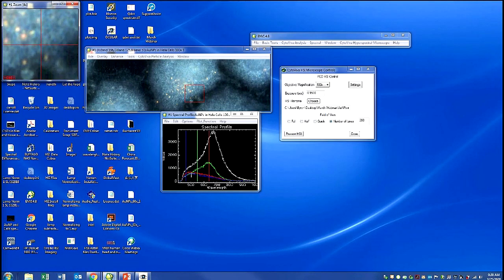The first thing that you noticed is that on one of the gold particles, we had a really high relative signal amplitude of almost 4,000, as opposed to about 800 on the cell structure, right? Which makes perfect sense if you think about plasmonic nanoparticle scattering and the intensity of that scattering being significantly more than what you would expect from the cell structure itself.